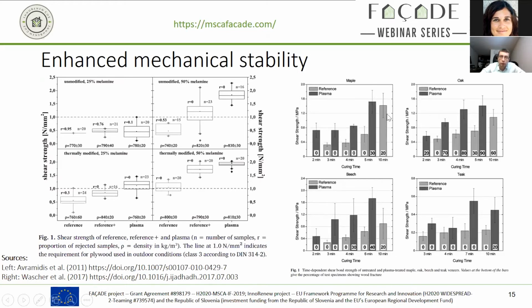We also see for different wood species that plasma pre-treatment and then gluing with melamine increases not only the shear strength of the bond but also enhances the curing, so it shortens the curing times. Not in all cases, but in some cases this was notable, as published in the paper. So this is something that can be used, but as is obvious from this overview and from the previous slides, this really differs between the materials used.